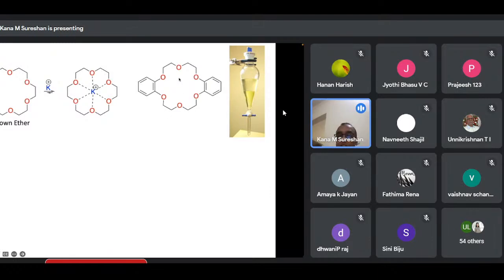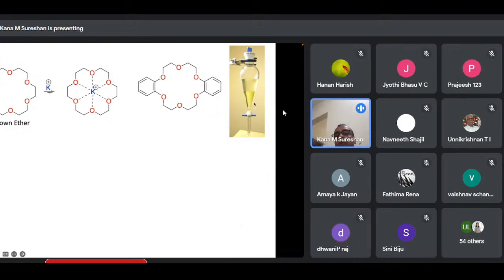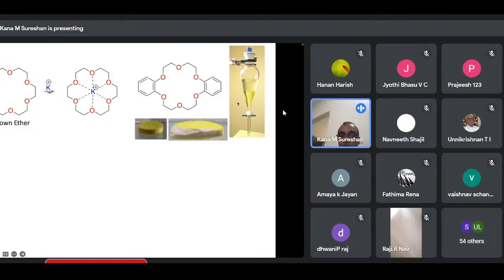Unfortunately, this cannot be directly used because this is insoluble, and only the surface, the potassium will be on the surface of these particles, not really inside, just like the carbon dioxide case I have mentioned. So usually you need a liquid-liquid extraction. You have to dissolve this in chloroform or some other solvent, then shake with water, then it will bring the potassium ion to the organic layer. This is not practically feasible for cleaning our drinking water.